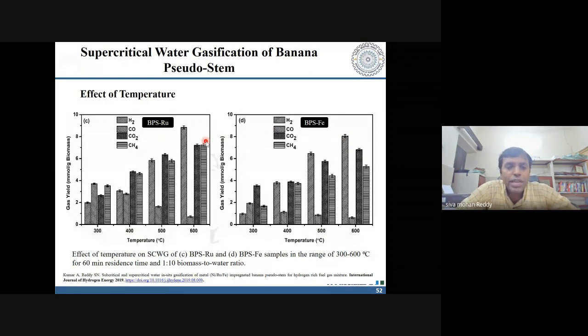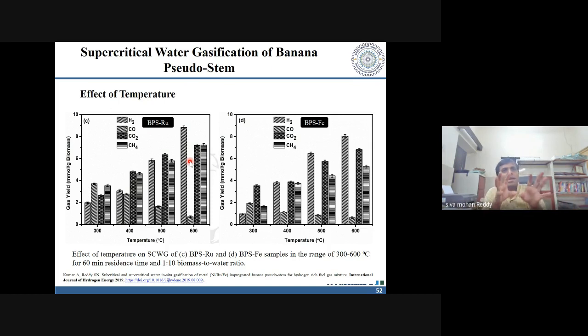Now, coming to the ruthenium and iron, the ruthenium also followed a similar pattern, but the gas yields are less compared to the nickel one. Ruthenium has a high activity towards the cleavage of CO bonds and results in the formation of methane also. If you look at the carbon dioxide yields and methane yields at 600 degrees centigrade, they are almost equal, which means that the carbon dioxide that is formed is cleaved in the presence of ruthenium, and thereby you are able to enhance the methane yields also.